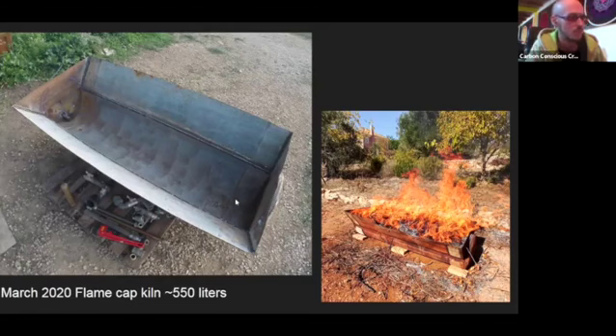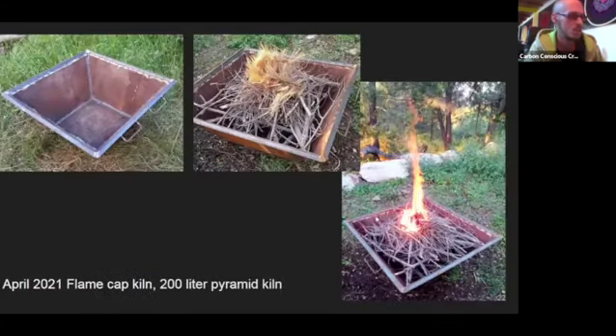But with flame cap kilns, it's the size of the opening on the top that determines how much biomass you have to keep adding all the time. So the bigger that is, the quicker you have to run to keep up with it. Especially if you feed it with very twiggy and thin branches, which is my preferred feedstock, because the thinner the branches are, the hotter the fire will burn. So this is a second flame cap kiln I built, which was a lot smaller, about 200 liters, and also much more portable, which then made it possible for me to start doing burns at other people's places as well.